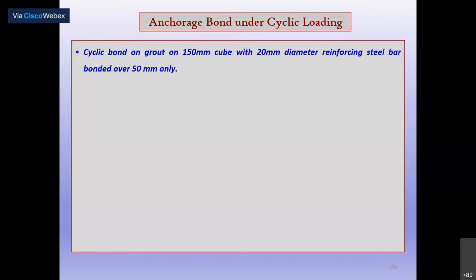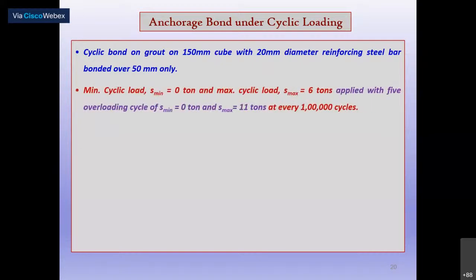The reinforcement will be subjected to cyclic loading. They are the end reinforcement bars in a system. The end regions are very dangerous under anchorage loading, anchorage bond. The anchorage bond behavior under cyclic loading is important. So it is a study we undertook, and also the bridge elements will be subjected to overloading. The design loads are minimum load 0 and maximum load 6 for the design of the bridge. But intentionally, after 1 lakh cycles of loading and unloading, the member is subjected to a minimum of 0 and an enhanced maximum, like 11 tons instead of 6 tons.